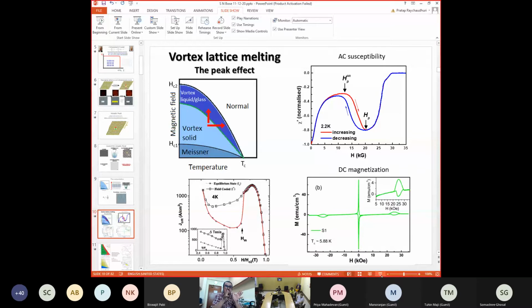Now, this Abrikosov flux line lattice is like a virtual solid, though it's not a solid made of physical objects, it's made of these flux tubes, but otherwise it has all the properties of a solid. So if you heat that solid, it can melt. If you apply pressure on the solid, here the equivalent of pressure is to increase the density of flux tubes. When you apply pressure, you increase the density of atoms. Here you want to increase the density of these flux tubes, which means you increase the magnetic field. So increasing magnetic field is the same as increasing pressure. That can also melt this vortex lattice.